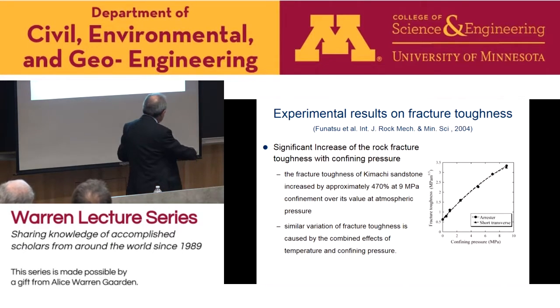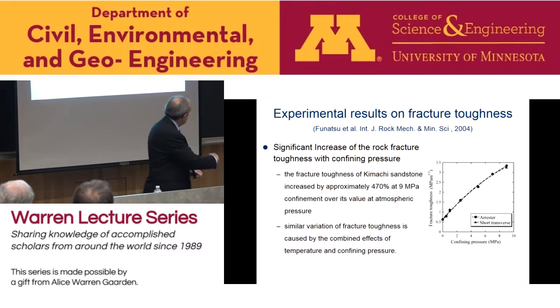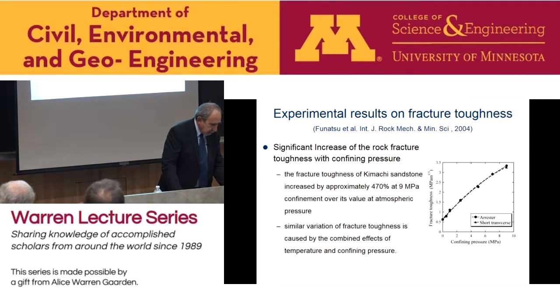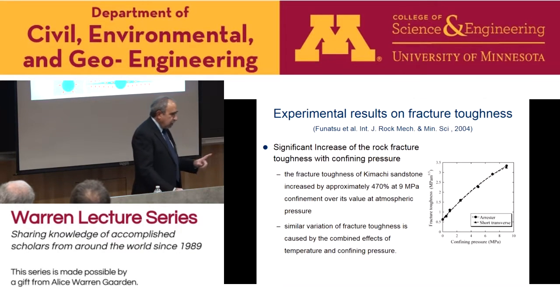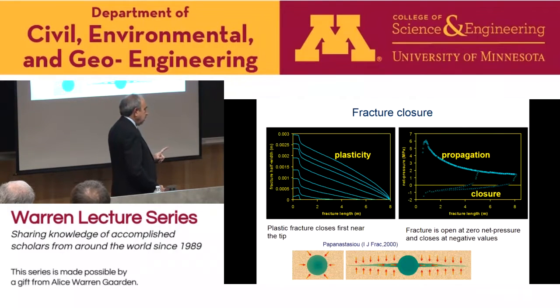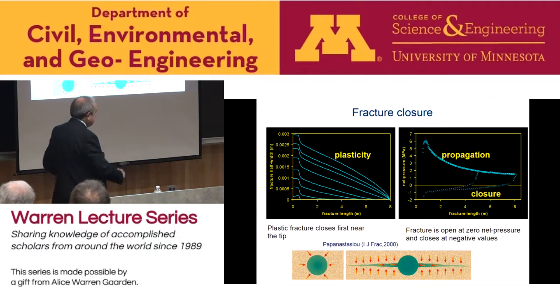Just how the fracture toughness varies with the confining stress. And even under isotropic stress field, probably this increase will be higher under anisotropic stresses. The other thing I looked at was the fracture closure, okay? How the fracture closes when it's created in a weak rock, which yields, okay?